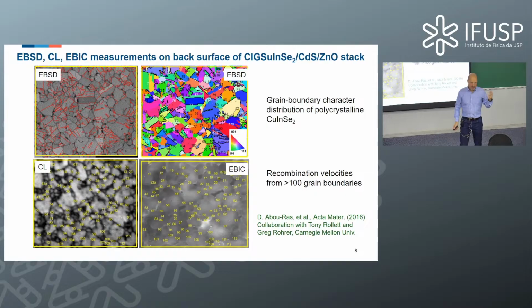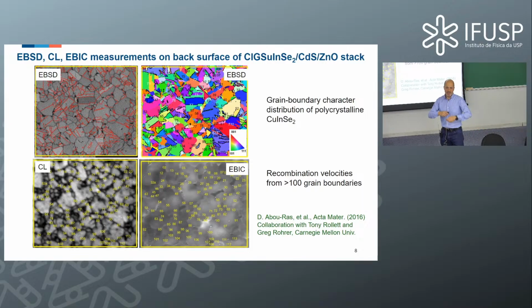What I will concentrate on, as I told you, is grain boundaries. This is an example where I combined EBSD, electron backscatter diffraction, CL, cathodoluminescence, and electron beam induced current. This is basically the local short circuit current that you can measure when you use the electron beam as a light source to generate electron-hole pairs. If you apply these techniques on identical positions, you can see that by means of EBSD, you can easily detect the local orientation of grains. You can detect individual grains, which means you can detect the grain boundaries, and you can also categorize them. You can tell whether it's a high symmetry grain boundary, like a twin boundary, or a randomly oriented grain boundary. And you can see that I gave numbers, so there are more than 100 grain boundaries that I investigated. It was quite a lot of work.